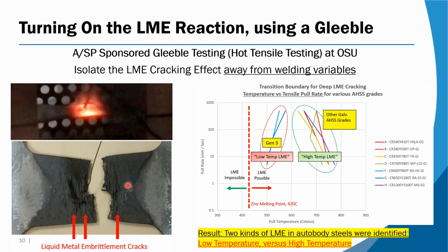They have one at Ohio State, and ASP sponsored a project to examine whether you get LME at different strain rates. Okay, tensile strain is one of the inputs, one of the bubbles on the Venn diagram. The other one is temperature causing the liquid metal. So we have this XY space that we did a lot of hot tensile testing in.